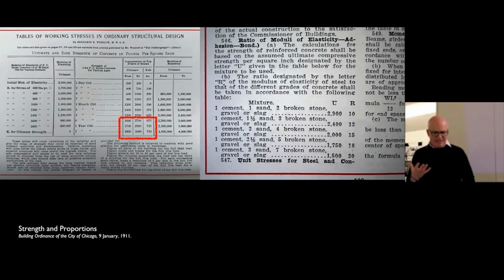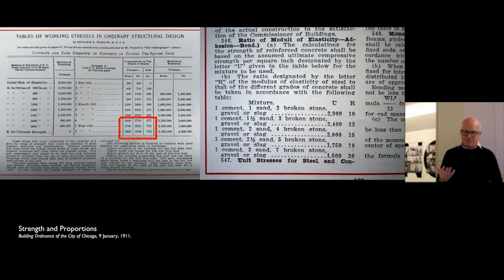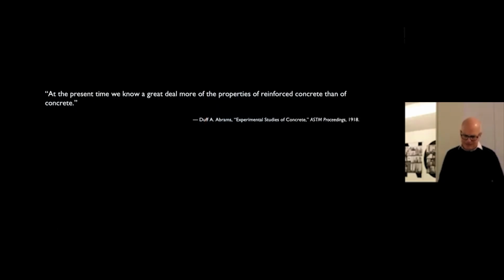Part of the problem is that this is also from the 1911 code, and it tells you basically it's a prescriptive code. It tells you exactly what the mix of the concrete has to be. And you can see that it's a proportion of cement to sand to broken stone or aggregate. And in particular, there's a mix that's 1 to 2 to 4. So 1 part cement, 2 parts sand, 4 parts stone. And you can see that the code says the ultimate strength of that is about 2,000 PSI. And it varies between 1,500 and 2,300 depending on how much aggregate you have there. But the error bars on this, again, are huge. And part of the problem that Talbot understands and that his lab begins to understand is that those error bars are part of the issue with understanding concrete.